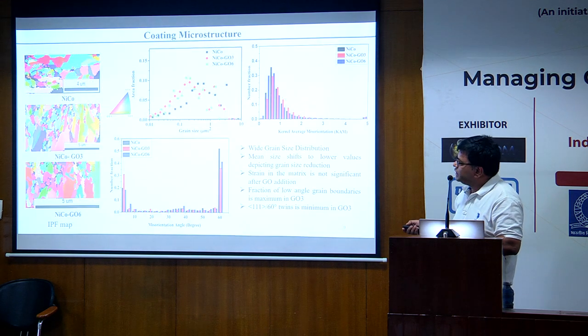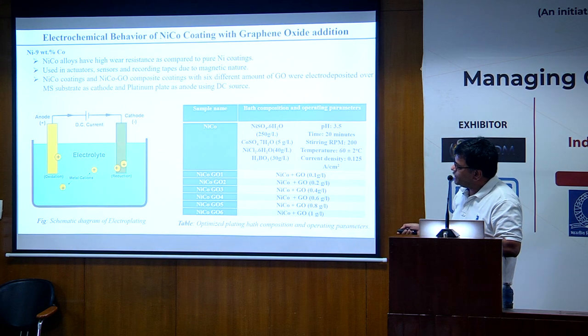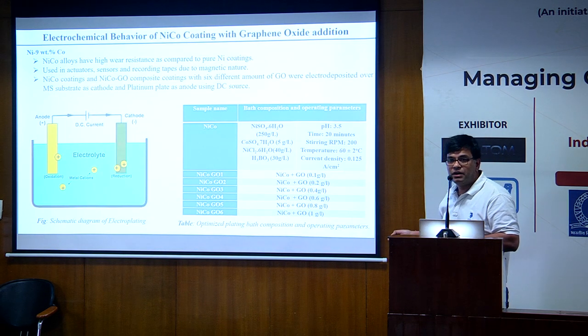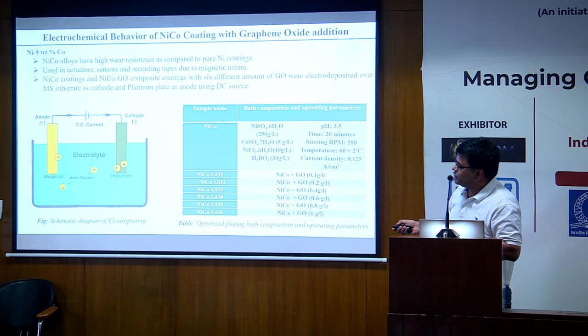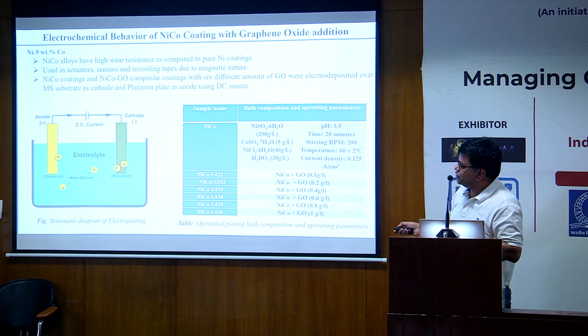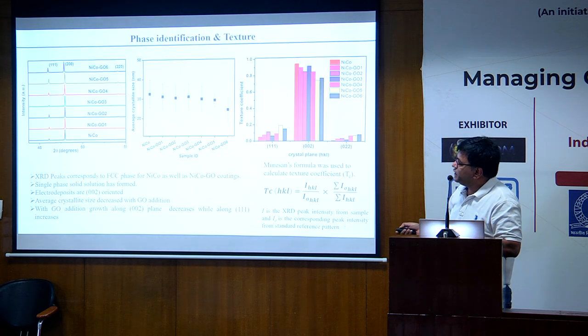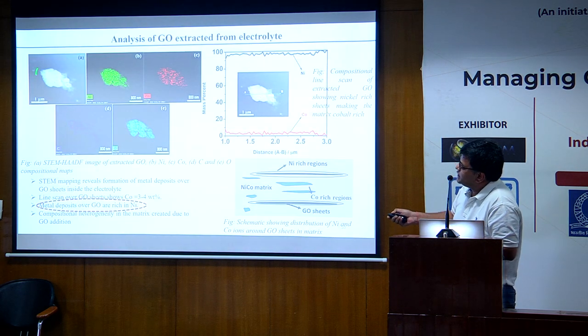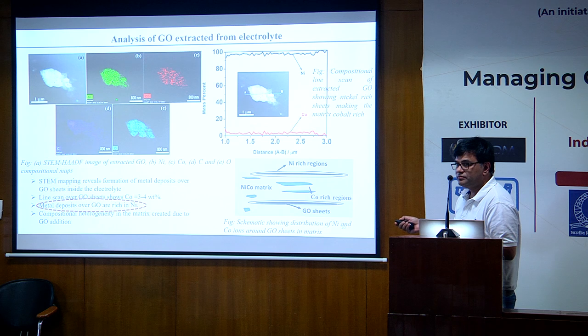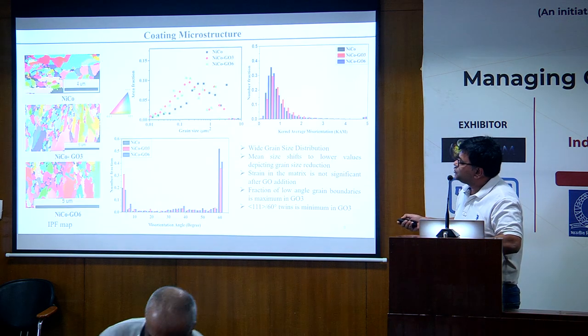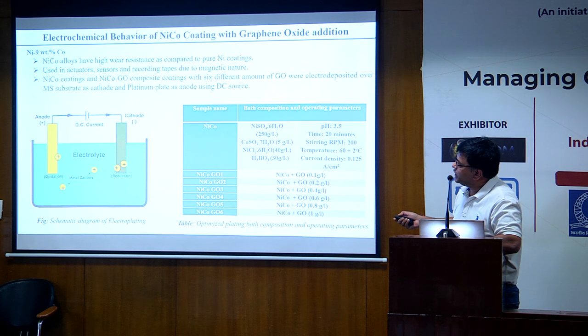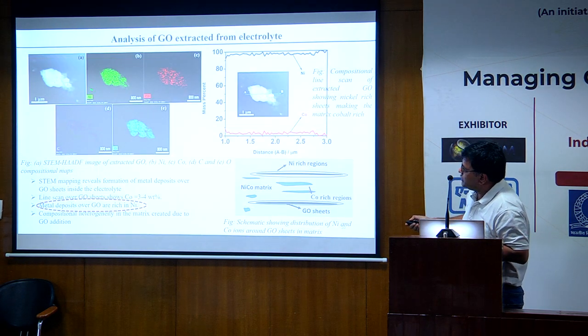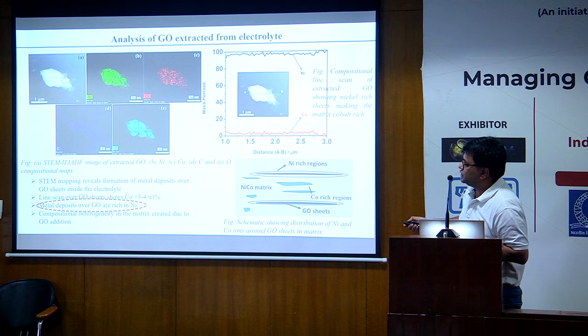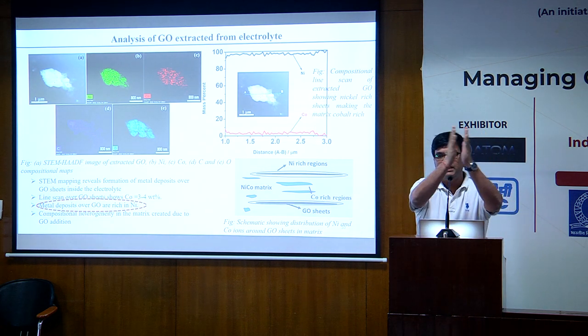So what we do is that if you see this coating bath, when the coating is happening, the graphene oxide is dispersed in this electrolyte bath. We took some amount of graphene oxide from a syringe right next to this cathode where the plating is happening. We extract this solution right from here, and we see the graphene oxide in the microscope. And what we observe is these are the images of the mapping. And what we observed is that the graphene oxide is basically highly rich in nickel. So the nominal composition of the coating should be 9 weight percent cobalt, but the graphene oxide that we actually see has a cobalt of only 3 to 8%. So the graphene oxide is going to get coated in the coating.